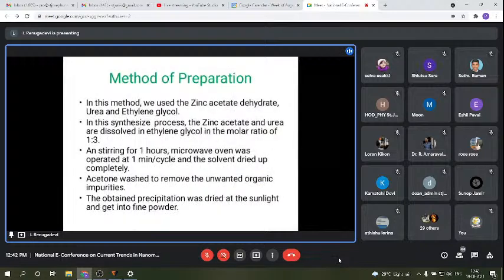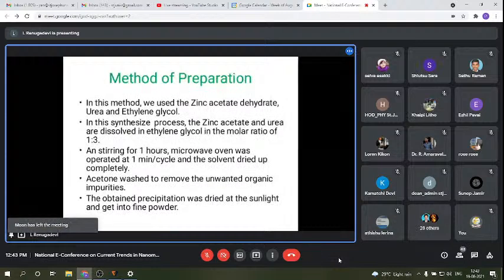In our method, the preparation is explained here. We use zinc acetate dihydrate, urea and ethylene glycol. In the synthesis process, the zinc acetate and urea are dissolved in ethylene glycol in the ratio of 1:3 and stirred for 1 hour, then heated in a microwave oven, 1 minute per cycle, until the solvent dries. The product is washed with acetone to remove unwanted organic impurities, and the obtained solution was dried in sunlight to get a fine powder.